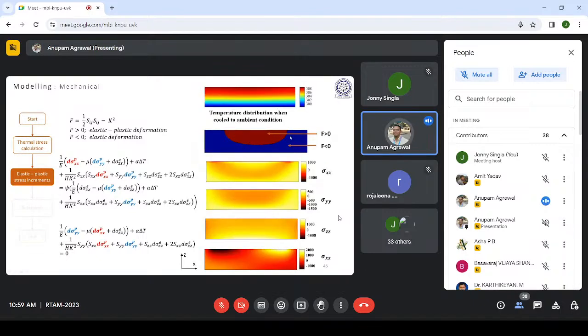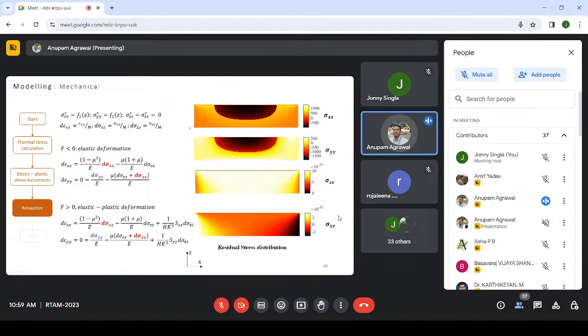Based on this, the melt pool region is all plastically deformed, and all the regions far away from there are elastically deformed with almost no stress. So the stresses which are built up try to relax, whereas where no stress is built up, it will try to resist, leading to residual stress formation. So this residual stress distribution is because of slow cooling. If you see, it is all cooled to room temperature, and the residual stresses are slowly getting built up as the temperature goes down.